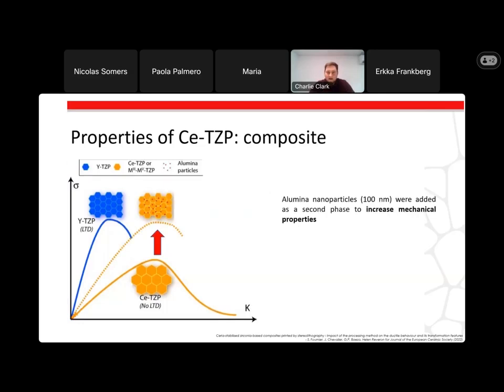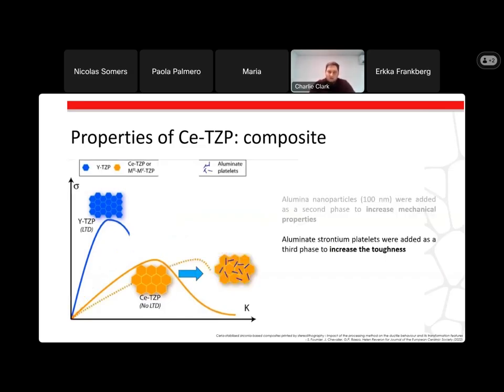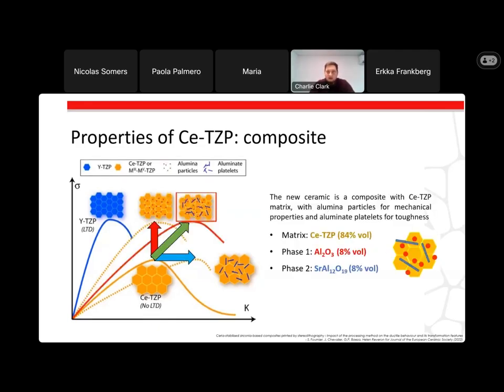So to balance this out, the powder had alumina nanoparticles added as a second phase to increase the mechanical properties. And to get the right compromise between mechanical properties and toughness, there was a third phase, with aluminate strontium platelets added. This meant at the end, we had a new ceramic composite, based on a cerium stabilized zirconia matrix, but with alumina particles for mechanical properties and aluminate platelets for the toughness.